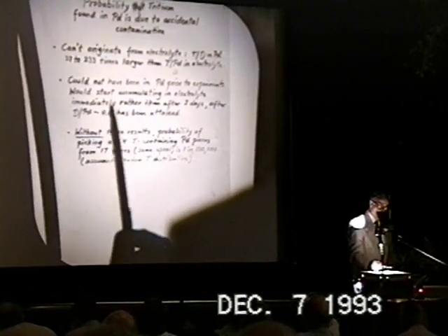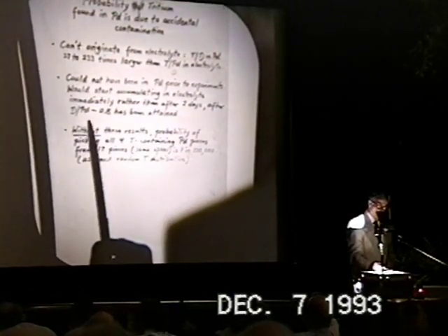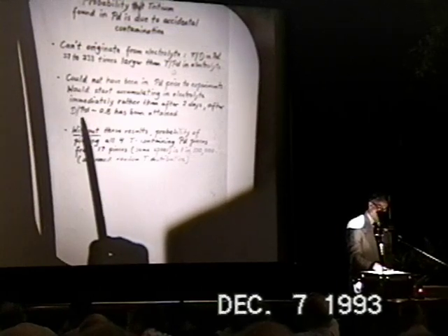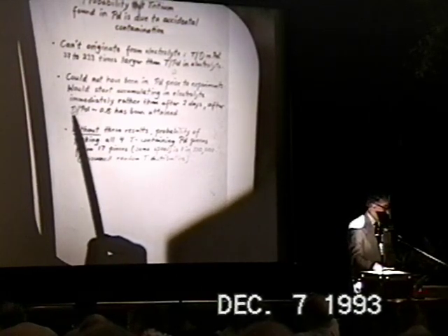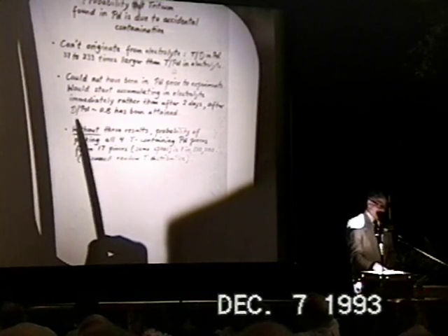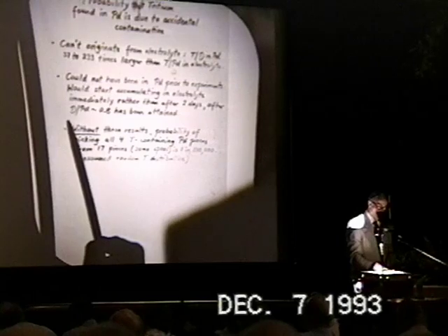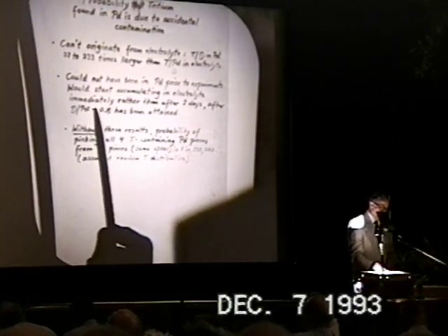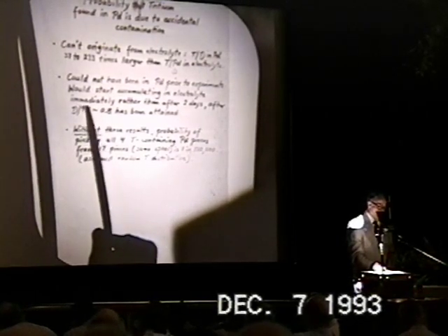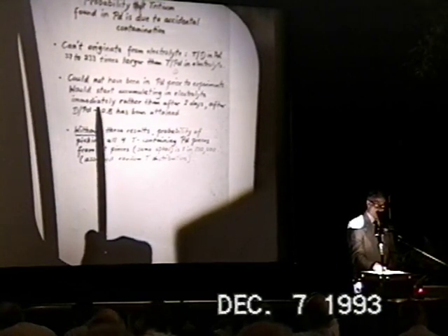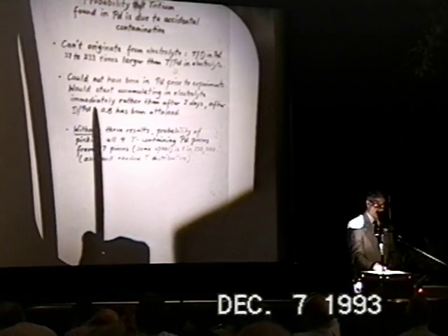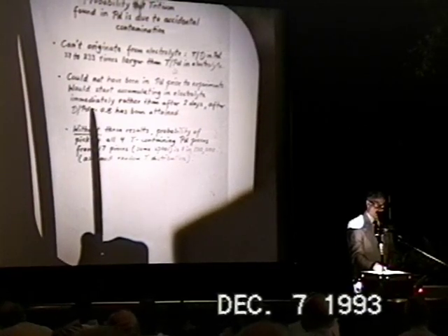We also contend that the tritium could not have originated with the palladium prior to the experiments. If that would have been the case, tritium would have started to accumulate in the electrolyte immediately. One calculates the diffusion time needed for tritium contained in the palladium to get out and give the first signal within the sensitivity of the method, and we calculate about half a day.